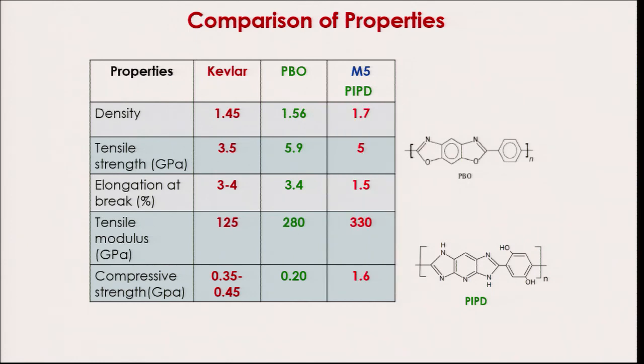the three, right. So, if I look at this material and if it is processed in the same manner to convert it to the fiber, then the properties which I expect are obviously even better than PBO, right. Let us compare. The properties are comparable, higher density, the tensile strength pretty high, 5 GPa, elongation at break has even further gone down because the structure is more rigid.